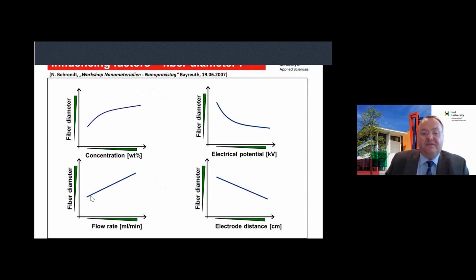The same effect we observe with the flow rate. Let me say, if you have a high flow rate, you create bigger drops or droplets, and therefore also higher fiber diameters. And then we have also the effect of the electrical potential. The electrical potential is the voltage divided by a certain distance between the electrodes. And if you have a high electrical potential, you have a high inducement of the droplet to start the jet, of course, and therefore if you have a high electrical potential, of course, you have a low fiber diameter.